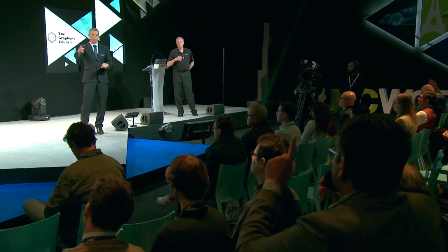The 19 samples that we had, 2 of them didn't have any impact on the brittleness, and I believe if we had optimized, really looked at the functionalization, tried to optimize the system for it, we could have improved the toughness. So I do believe that you can get improvements in toughness. It's just very critical for you to understand how well it's bonded into the resin and getting it dispersed in the resin.